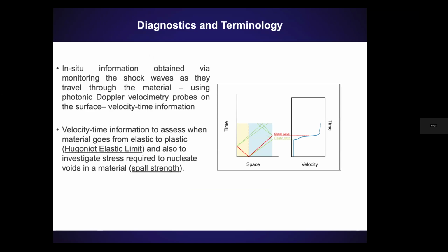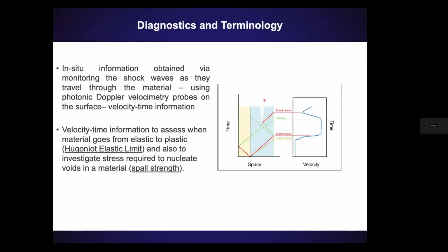Okay, perfect. So basically, the point I was trying to make here is nothing really happens. You don't measure anything in the PDV until something happens at the free surface. So these two waves get to the surface, the material gets shocked up, then the signal stays constant, nothing is happening until this release happens and the shock gets caught up between this small scab and the free surface, and you get this ringing type behavior.